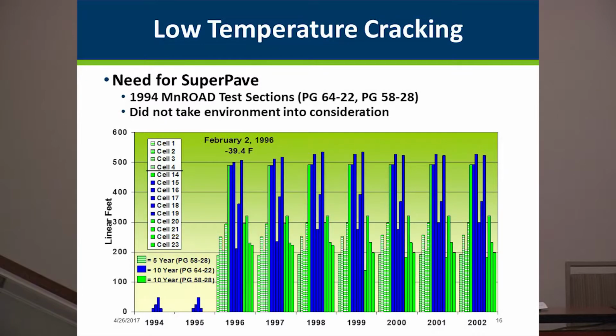This chart shows the need for Superpave, the need to address the environment. And we looked at test sections that were 64-22. Those are the ones that are in blue. Then the 58-28, again in green. You can see how the 22 cracks a lot. It cracks after a couple of years. We got down to minus 39, and the whole system cracked after 2 years in 1996. You can also see the fact that we had 5- and 10-year test sections, which is interesting there because